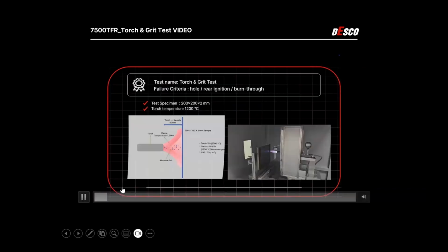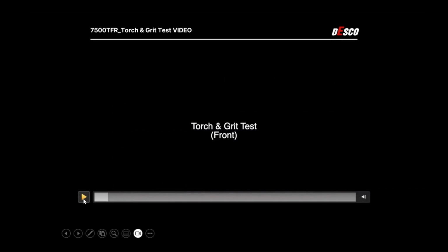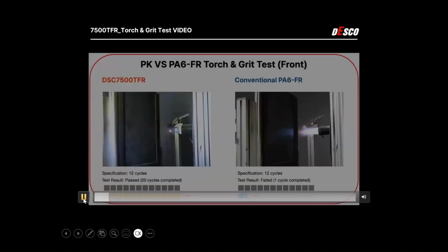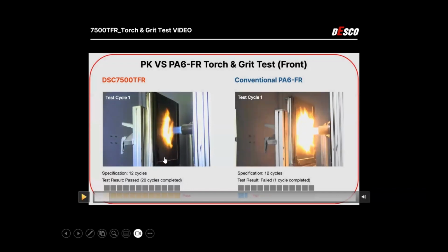Here is the demonstration video. I'm going to skip the introduction about our grade. Just to make sure, this is our TFR grade, and this is the nylon 6 flame retardant grade. Here is our specimen. It's 2 millimeters thick, and the distance from the torch to our specimen is 60 millimeters. For 15 seconds, there's only flame over here, and for 5 seconds, there's flame and grit. That's one cycle, and let's see how long they endure this test.